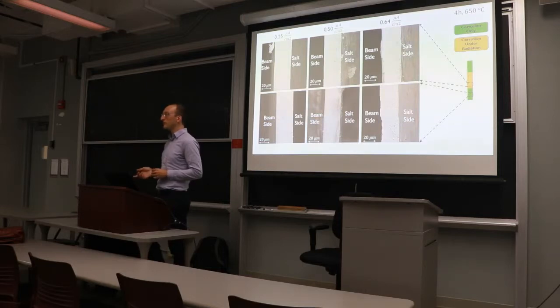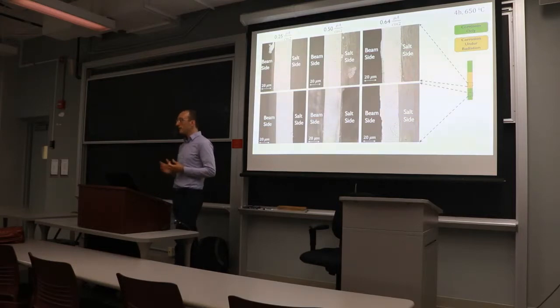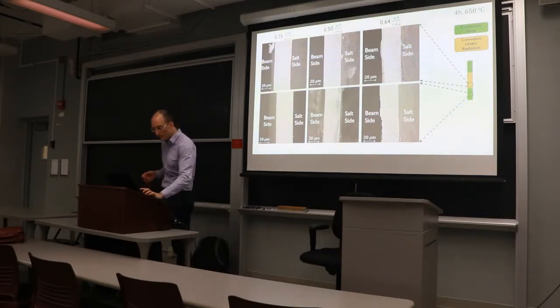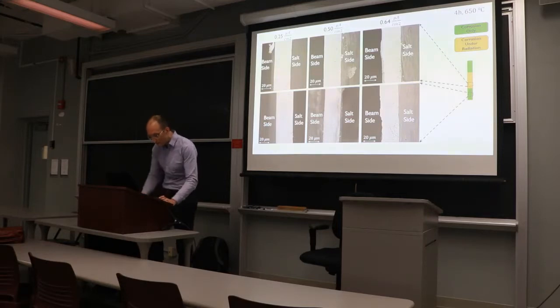The other controls that we do, that I didn't mention, in order to test whether this hypothesis is true: the effect should switch when you go to a non-alloy, like a pure metal. Because then the salt should get more corrosive and the spot in the center should actually get worse. So since it's coming up, I would like to show you the results of that experiment. Since I take it there's a pretty big molten salt community here.